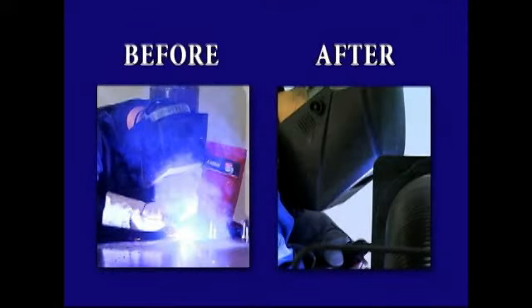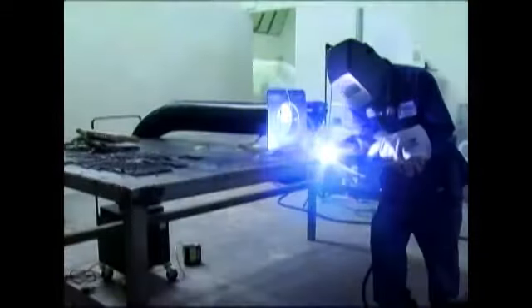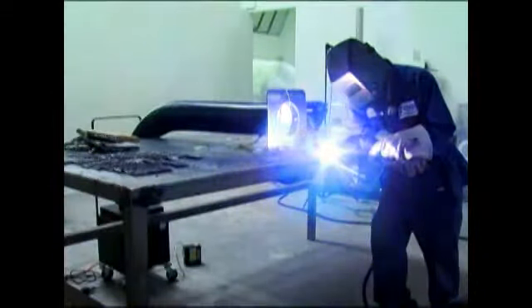The conclusion is that the machine is quite effective in capturing and controlling hexavalent chrome, and we saw that the exposure of the welder was well within the new OSHA standard of 5 micrograms per cubic meter as an 8-hour time-weighted average. Another condition that we wanted to test for was how effective the welding extractor would be in cleaning the ambient air in the welding shop.